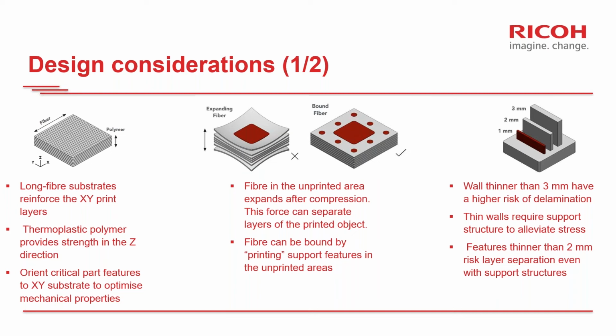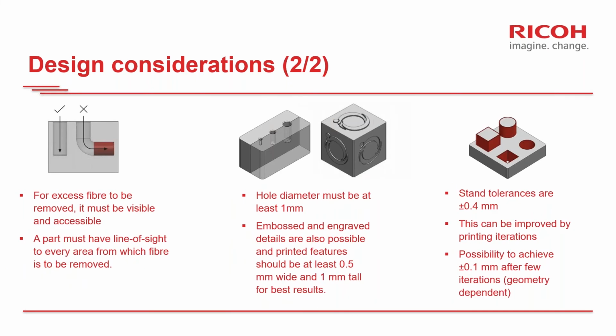Then, when it comes to fiber removal at the end of the process, it is important that the fibers are visible and accessible. So the parts must have a line of sight to every area from which the fibers need to be removed. In terms of other minimum features that can be produced, generally holes must have at least 1 millimeter in diameter. It's possible to create parts with texture on the surface, like embossing and engraving. For this type of feature, it must be 0.5 millimeter wide and 1 millimeter tall for a good definition.